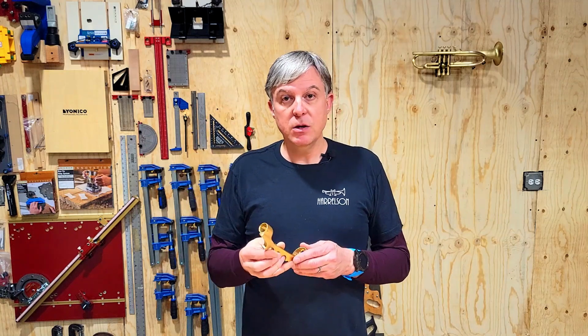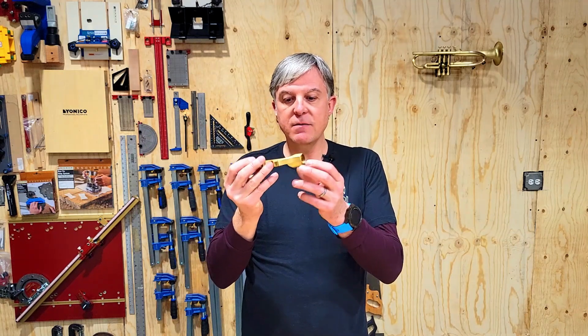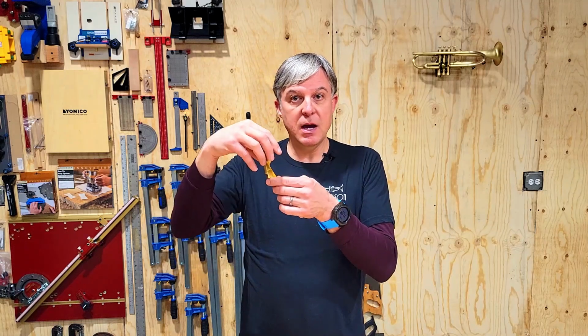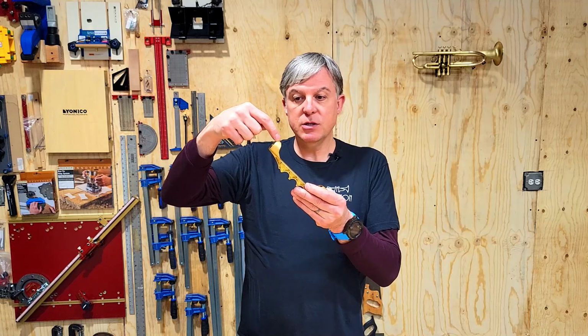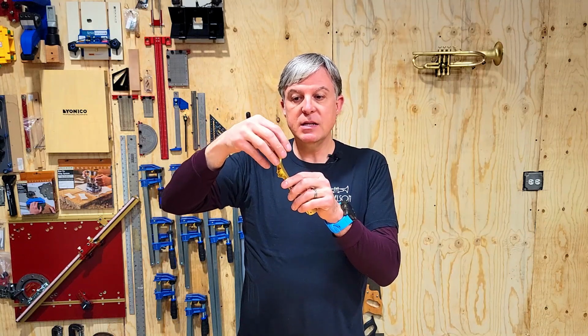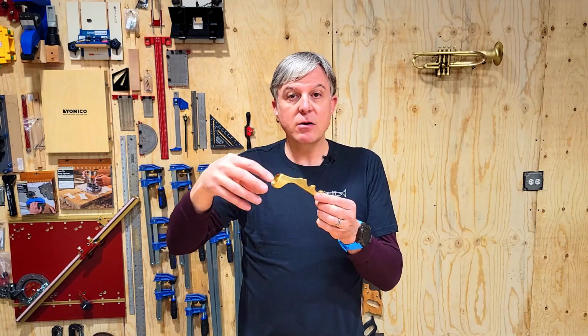So it's really interesting to note that all my studies in antinodes and nodal points and the excessive vibration interference that basically disrupts the sound of a trumpet directly correlates to machining the parts that we make. So the more material we remove, the more likely we're going to have nodes and antinodes in the material and in the end mill, and sometimes even in the machine, but mostly right at the cutter tip, that could create some kind of a harmonic frequency where the end mill is spinning at a certain frequency and this material is very thin. It can start to resonate, and as it moves, it creates patterns in the metal that are defects. And when that happens, we have to throw that part out. The thinner we machine something, the more likely that's going to happen.